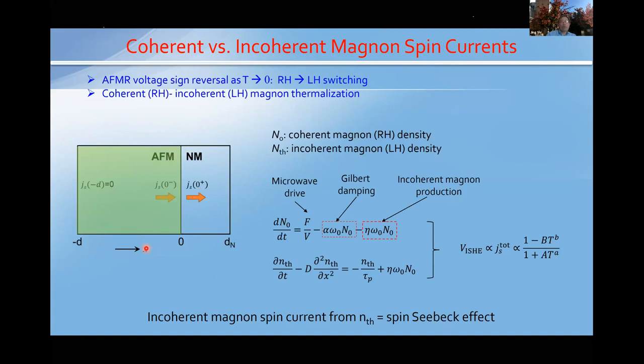So we developed a simple model to explain this feature. Here we have a rate equation for coherent magnon number or density. This is driven by a constant microwave source, which generates coherent magnons. And we have this Gilbert damping, which takes care of the magnon to phonon transition, magnon-phonon scattering, and we have fewer coherent magnons due to this process. But we have to add this term, which describes coherent to incoherent thermalization. We call this the incoherent magnon production term. We have to put in this term to explain this incoherent transition and the sign change below 45 degrees.